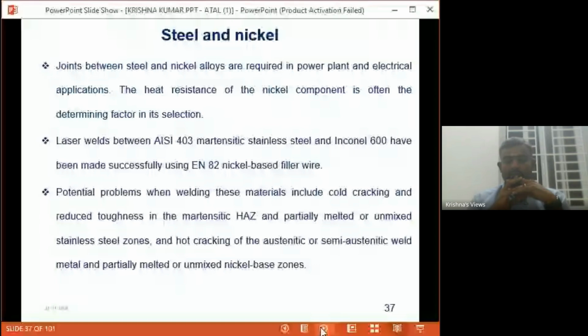The potential problems when welding these materials include cold cracking and reduced toughness in the martensitic heat affected zone, partially melted or unmixed stainless steel zones, hot cracking of the austenitic or semi-austenitic weld metal, and partially melted or unmixed nickel based zones. So these are all the existing problems.